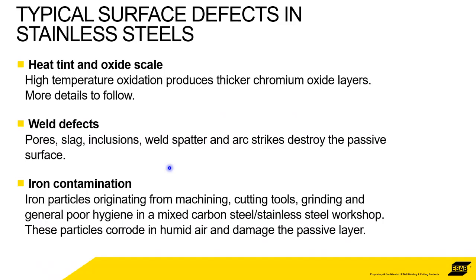It's a mechanical abrasion that's got rid of that chromium oxide layer. If the chromium oxide layer is gone, then you don't get corrosion resistance. If it's in air, then it will reform. Okay, but if you do have bumps and knocks on the surface, then it's an area where dirt and dust can accumulate, and that's another problem we'll talk about later again.